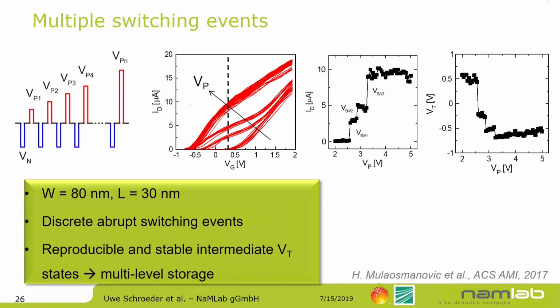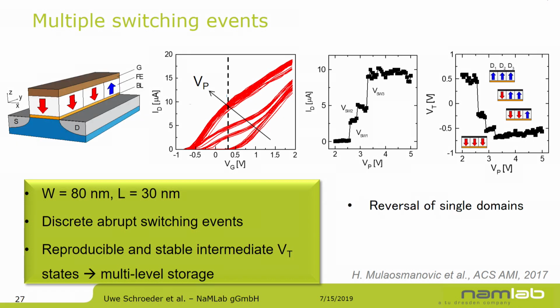And now, we looked at different devices. There were some devices where you have three switching steps, and overall you can explain everything if you have a transistor structure with 3 grains. By applying higher and higher voltage, you can first switch the first domain, then the second, and then the third domain, till you have completely switched all your domains within the transistor structure to the other threshold voltage.